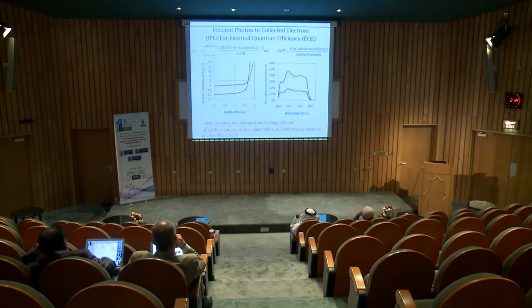Another type of data that we collect in addition to the current-voltage curve is the incident photon to collected electron efficiency, or, as it is called in the literature, external quantum efficiency. So what exactly is the EQE? You shine light on the device and measure the number of electrons collected per incident photon. You shine monochromatic light on your device and measure the photocurrent at each wavelength. And if you integrate the area under your EQE curve, it should give you the same short circuit current that you get from the current-voltage measurement.